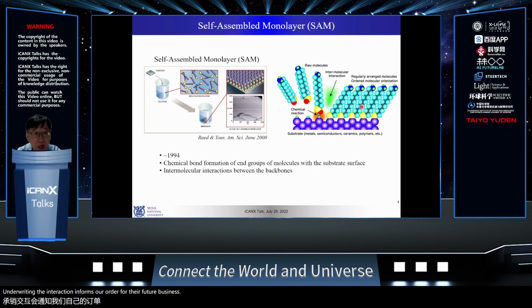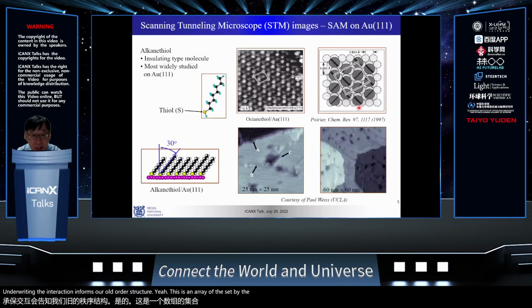Okay, this is an example of a self-assembled monolayer. I got the image from Paul Weiss, editor of ACS Nano. The molecule here is called alkanethiol. Thiol is a sulfur term in the usual chemistry community, and this thiol is known to bond chemically well on a gold substrate. So it forms like this, in cross-sectional view, and it tilts about 30 degrees on gold.